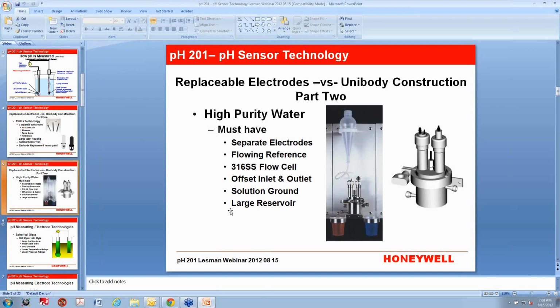And then, of course, we have the very large reservoir on top, which makes this an ideal sensor for measuring high purity water. And you really have to have it. You can't use something with a gel reference. You can't use the unibody construction because it just uses the KCl too fast. That's such a small volume. So you have to have this for high purity water, but it's not a very good sensor for any other application. So the replaceable electrodes are mostly used in power plants for high purity water.